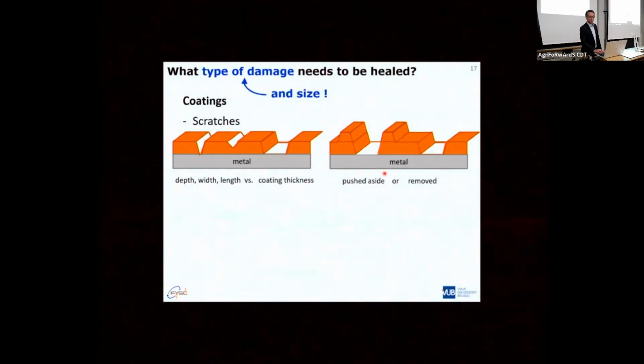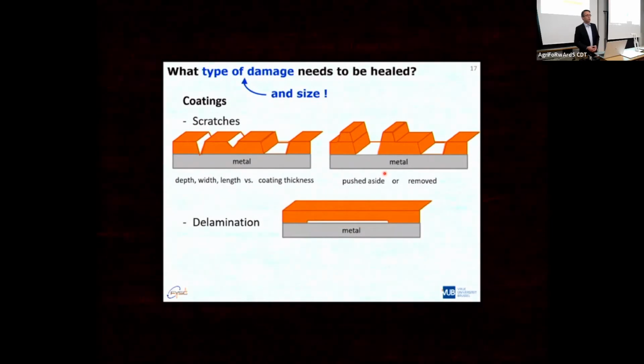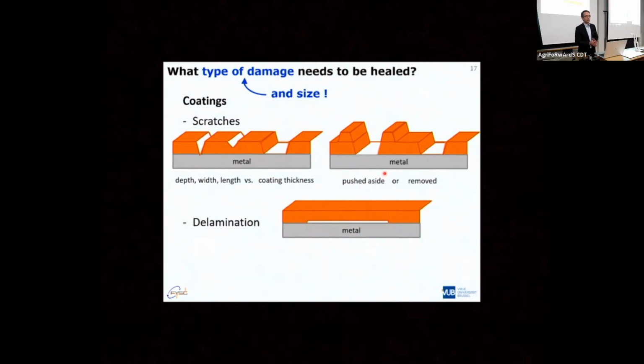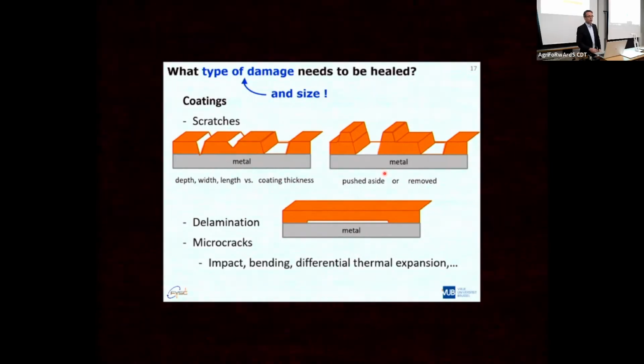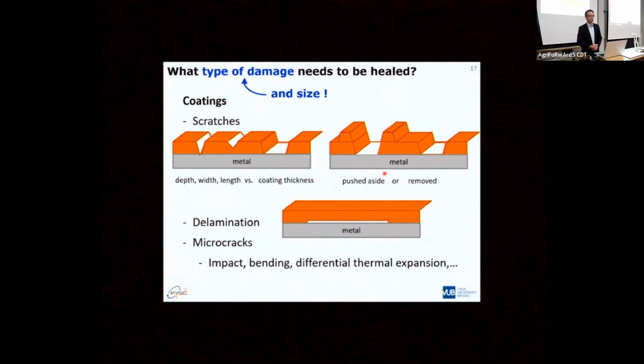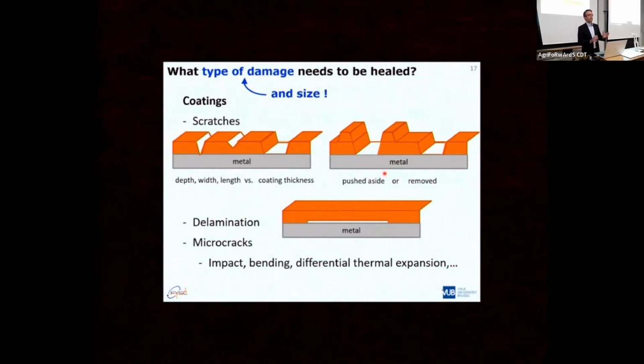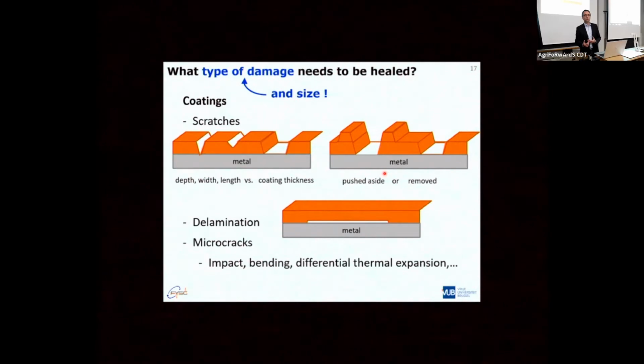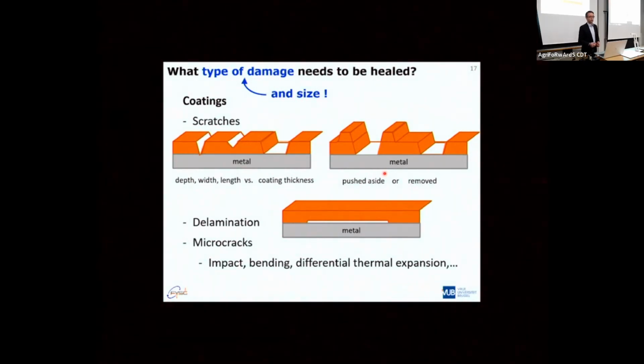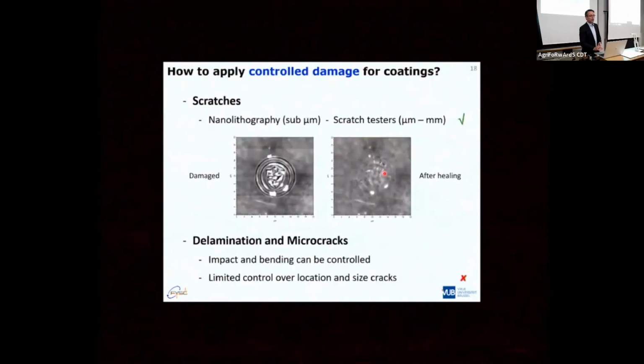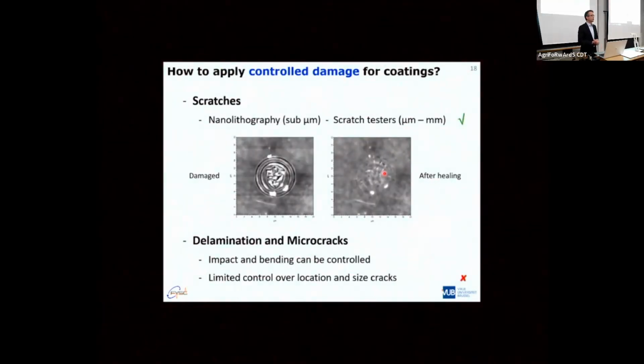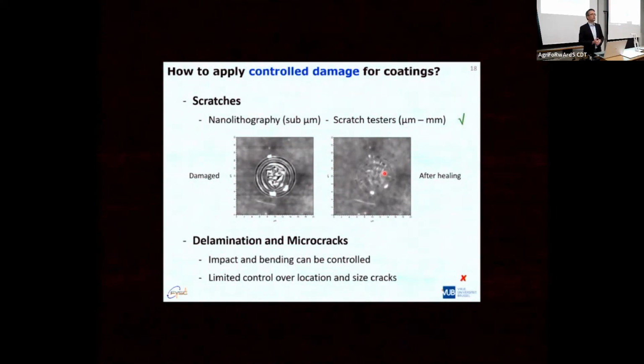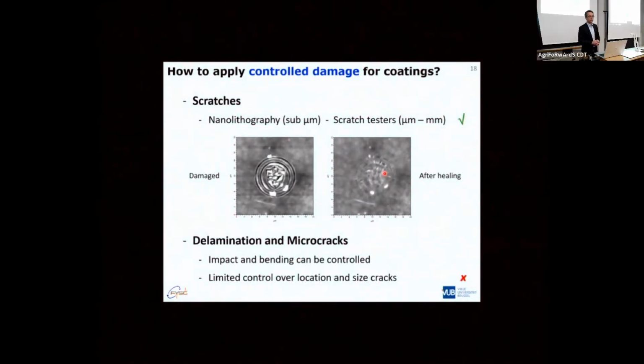But of course, these are not the only kinds of damage. You could also think of things like delamination happening as a result of maybe an impact, maybe bending, maybe a difference in thermal expansion coefficient of your metal and the coating that is on top of it. So for each material system, you will need to look at what is most important for the system and for the application in which it is going to be used. You can make scratches in a controlled way. You can do that with nanolithography and then make the symbol of your university disappear. It's a very nice way to see it. But it's maybe not the most quantitative way to show that you have a self-sealing or a self-healing system in this case.